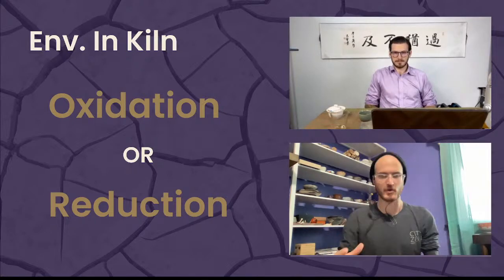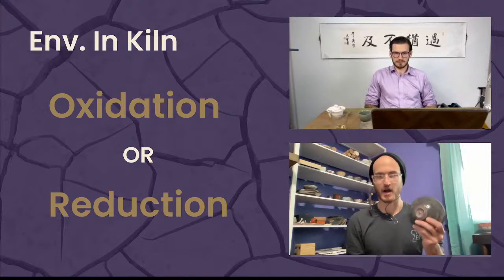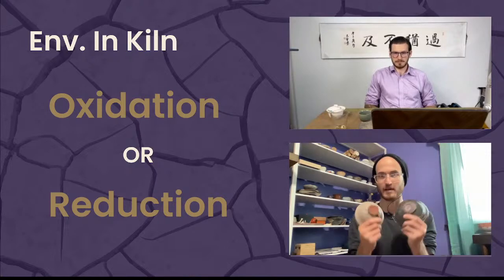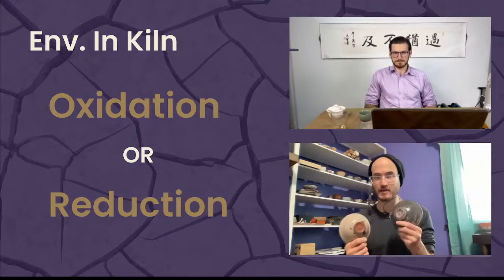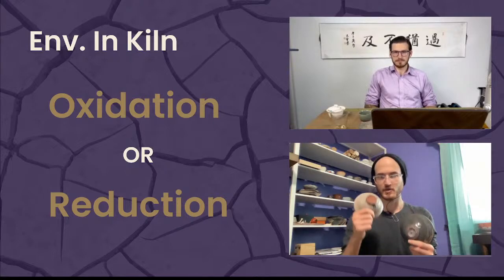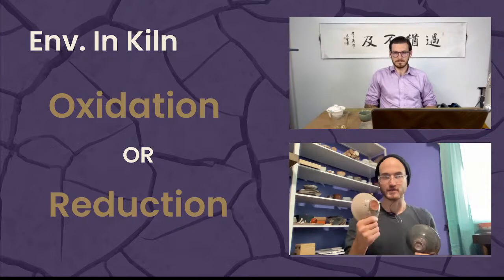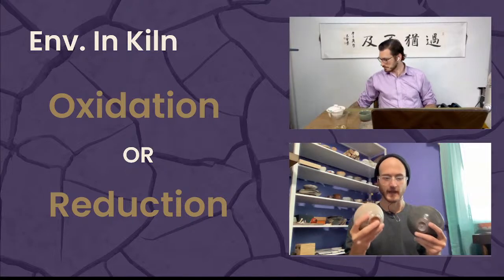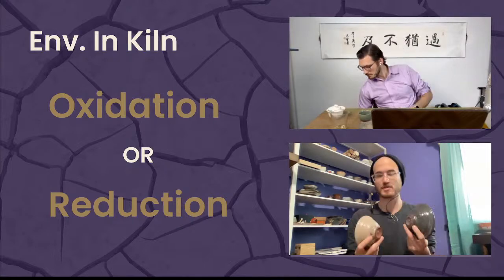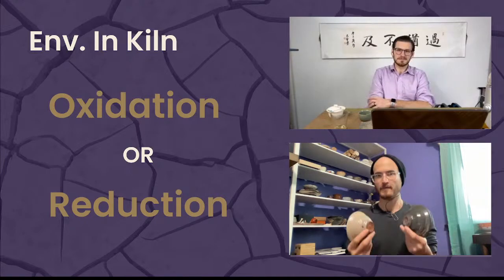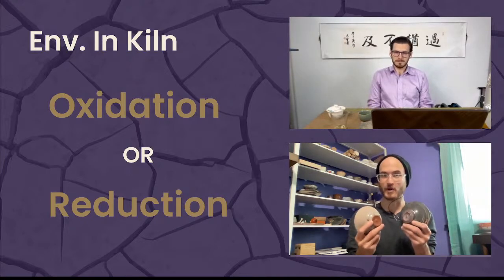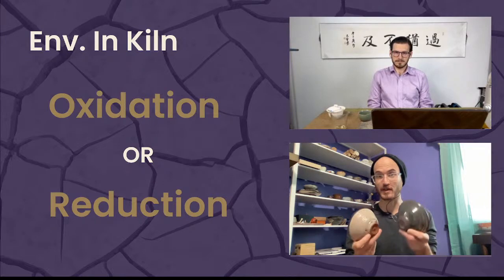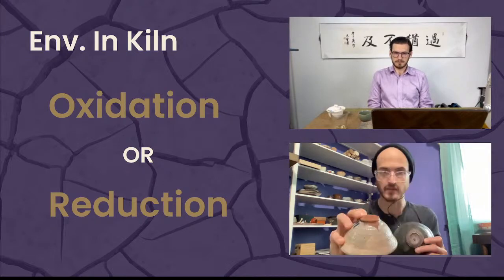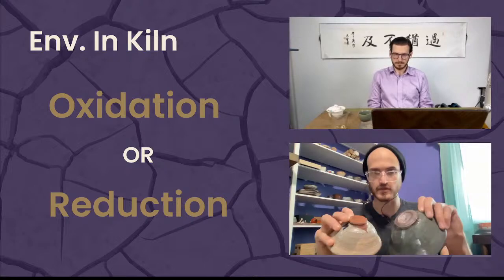But the chemical phenomenon is that you're pulling oxygen molecules away from the wares inside of the kiln, and it's changing what the oxides are doing. So you start with red iron oxide, Fe2O3, and it's all throughout the clay, and there's lots of iron in the clay. And then because there's not enough oxygen in the kiln environment for efficient combustion, it's going to start ripping oxygen molecules out of your clay. And it'll change color from this bright brick red color to this darker burgundy color.